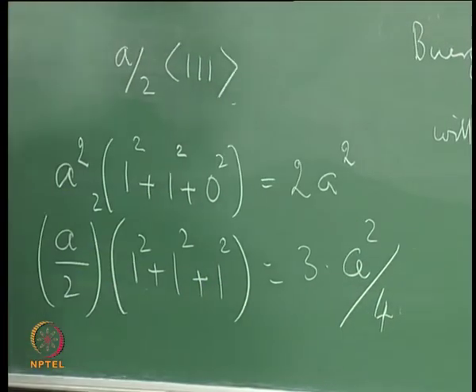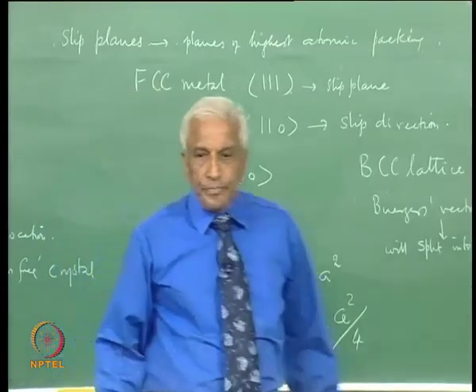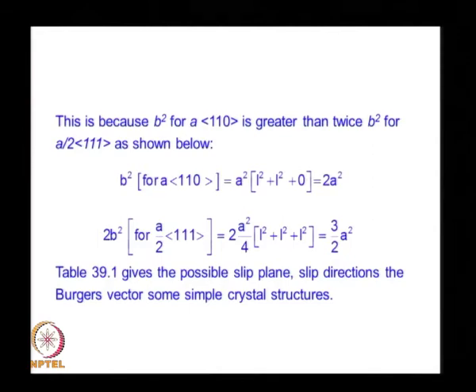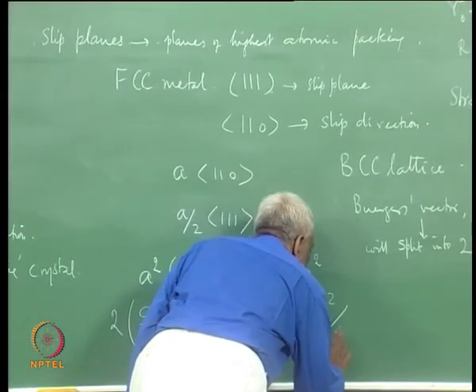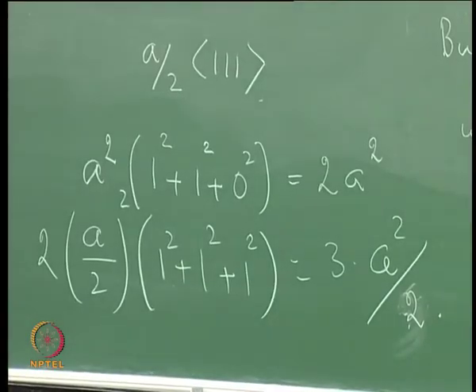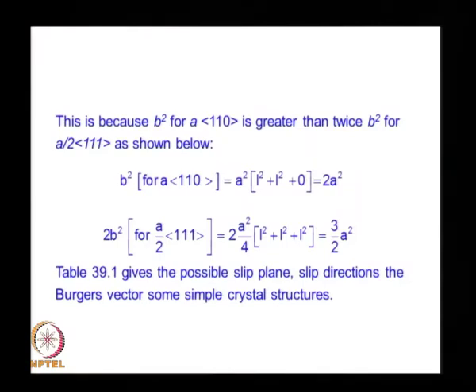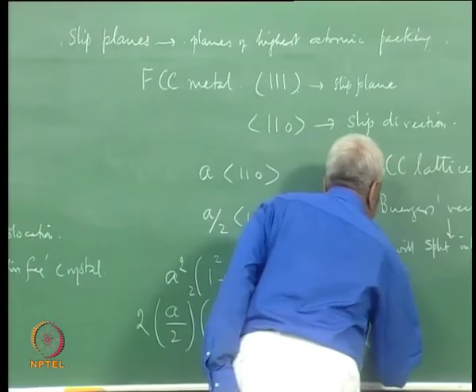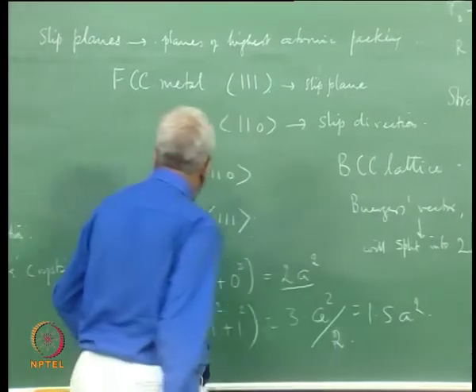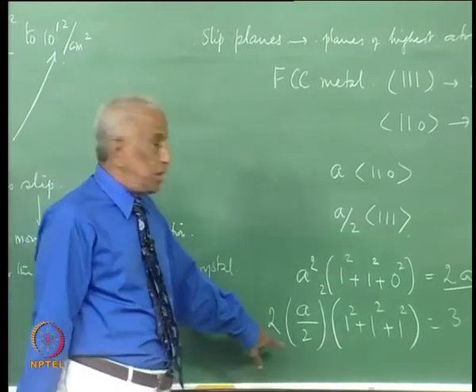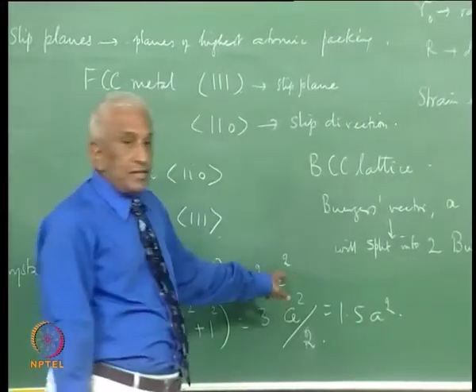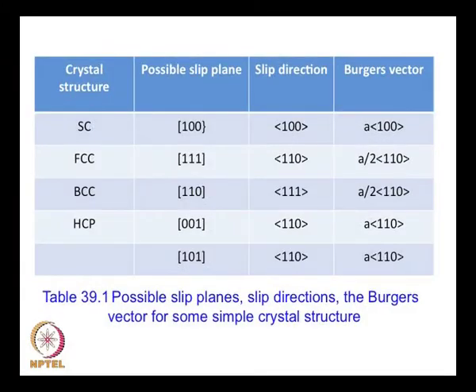Now, there are two such. So, this will be 3a square by 2, whereas this is 2a square. So, this is 1.5a square. So, splitting of this Burgers vector into 2 along <111> gives us lower energy than this. So, in table 39.1, we are given the possible slip planes and the slip direction along with the Burgers vector for different crystal structures like the simple cubic, face centered cubic, body centered cubic and HCP, hexagonal close packing.